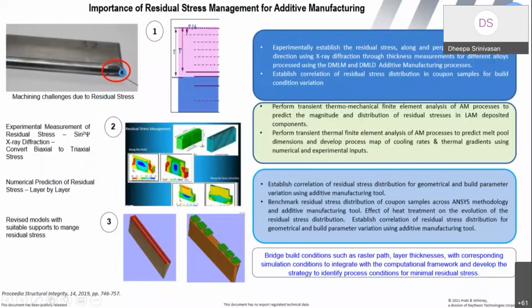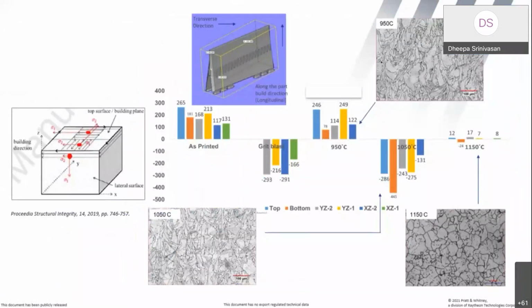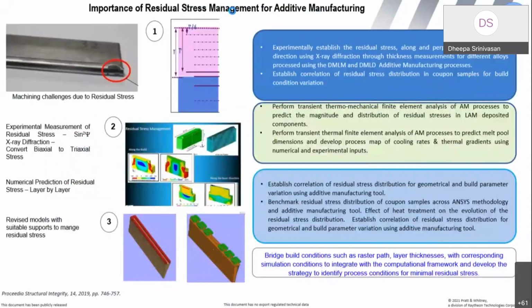Namely, while removing, there is so much tensile residual stress that you are not able to use an EDM wire cutter to remove it in a smooth manner. So residual stress is another very, very important challenge. Next, how did we measure it? I only wrote here: experimentally establish the residual stress along and perpendicular to the direction using XRD, through thickness measurement, etc. Establish correlation of residual stress and correlate it with the finite element analysis.